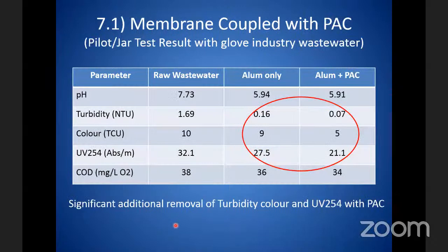So I have tried something. If we put powder activated carbon into the system, you can further remove turbidity from 0.16 to 0.07. You remove color from 9 further down to 5. And also UV254 absorbance. Just now I already explained UV254 is like DOC, dissolved organic carbon. So you remove another 20% more. So it is significant for turbidity, color and UV254 removal with powder activated carbon with the membrane.